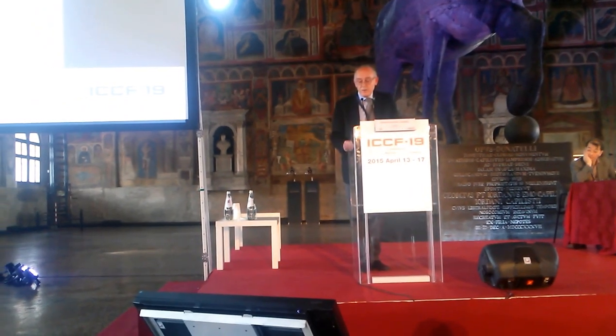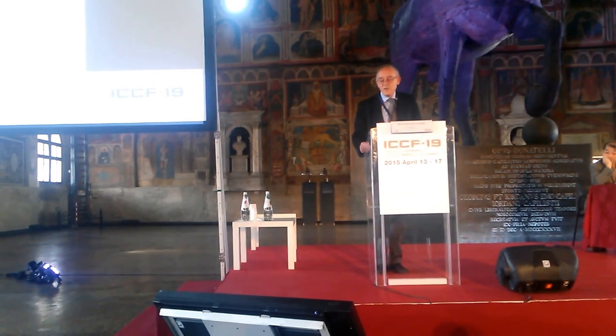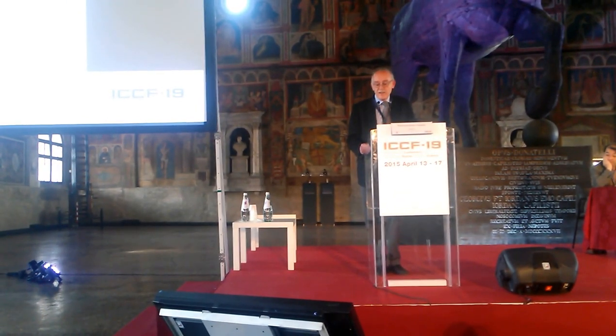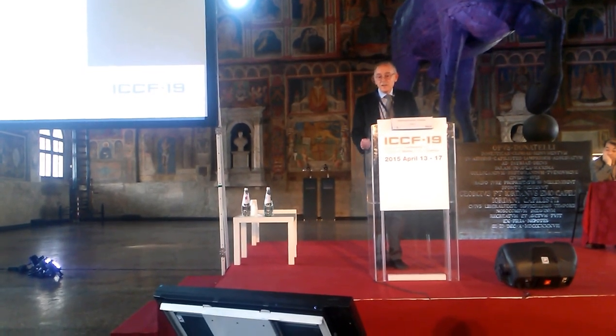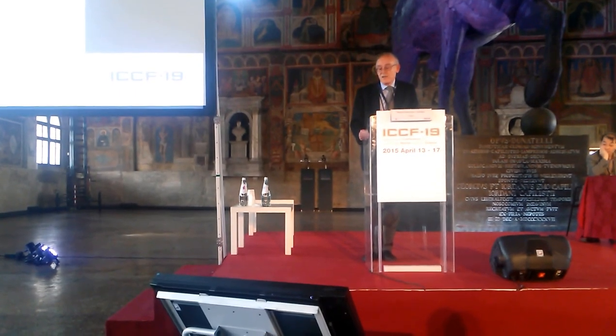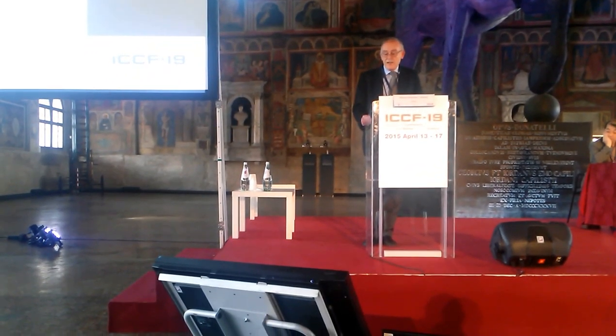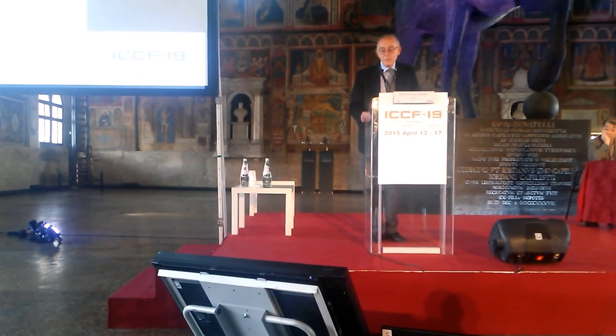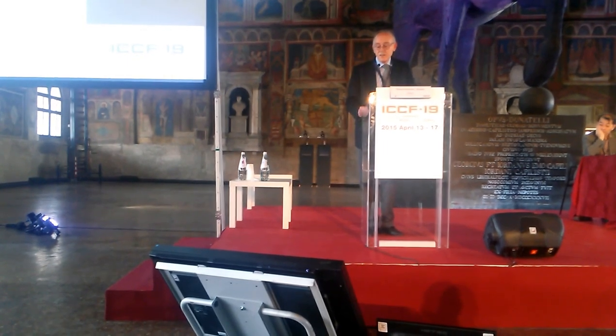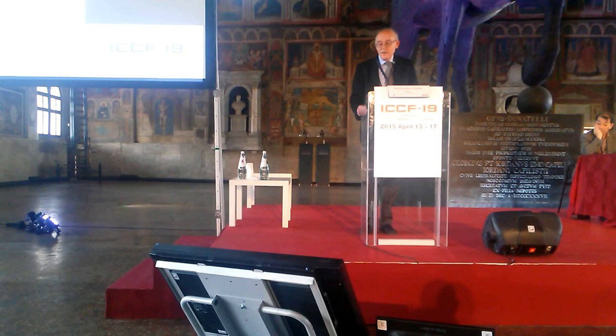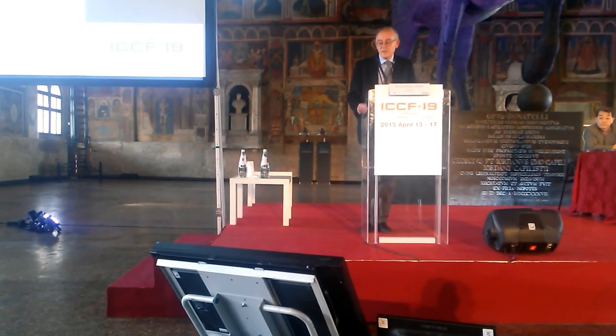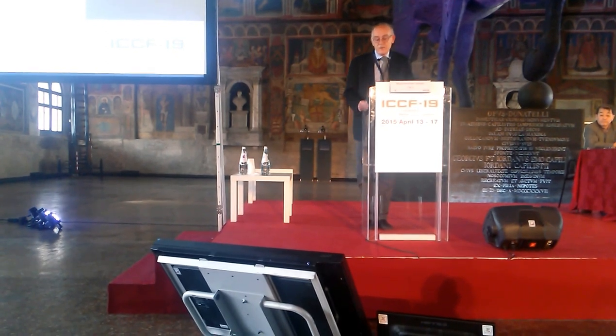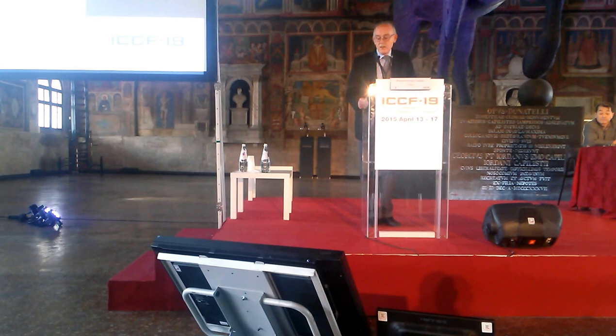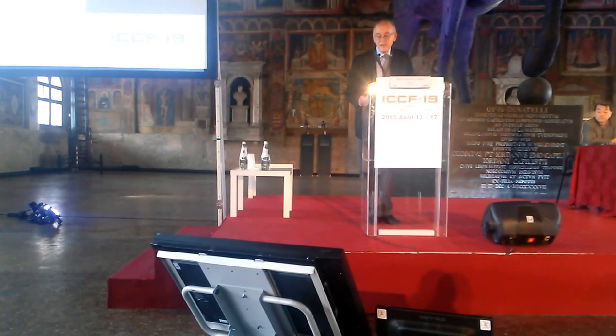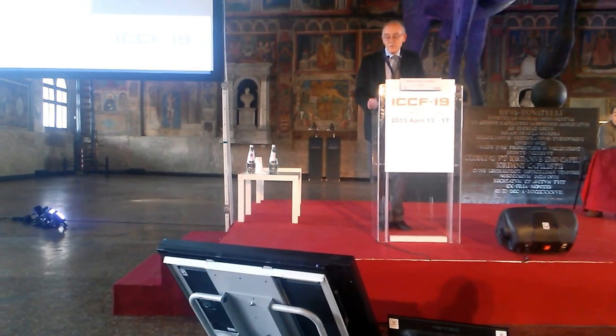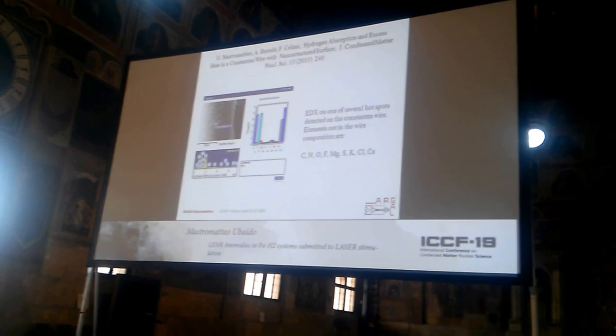Here I have reported an analysis of constantan wire coming from Celani lab, where we observed some extra heat production in hydrogen at 350 degrees. And analyzing some pieces of the wire, we noticed a few hot spots. And also in this case, we found in the hot spots lighter elements with respect to the composition of constantan. If you pay attention to the list, we are in front of magnesium, silicon, sulfur, and calcium very often.